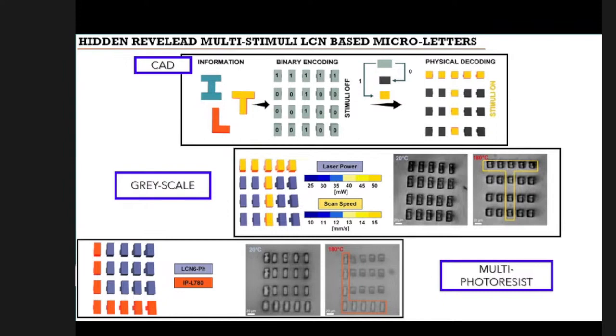But to emphasize the difference in contraction between the different pixels, I choose to use a multi-photoresist approach. So I combine the first lithographic technique with the liquid crystal mixture with another photoresist that is not able to contract under light or under temperature, which is the IPL. And in this case, the difference in contraction is higher. This kind of system, I demonstrated that can be used in the field of encryption, that is a physical encryption. In this case, we can obtain a device that cannot be attacked from the external, like with cyber attacks, and that can be triggered only with one stimulus.